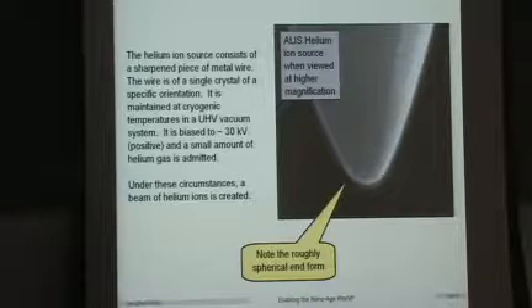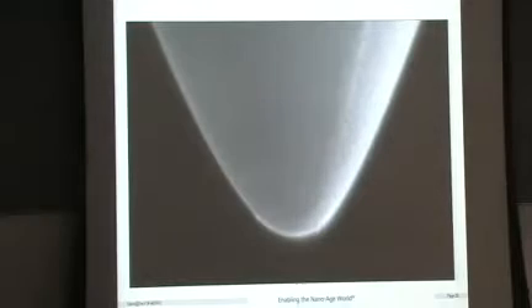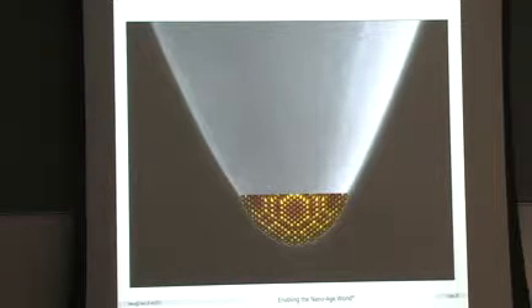And if it's made of a single crystal and is bounded by a sphere, you can imagine there's some very interesting structures that happen, because, of course, atoms are indivisible, but if it's a spherical shape, it actually has to have a faceted kind of end form. These are the atoms, if we could see them, on the tip. And this is the best atom-wise approximation to a sphere. Some of the atoms stick out more, some stick out a little bit less.